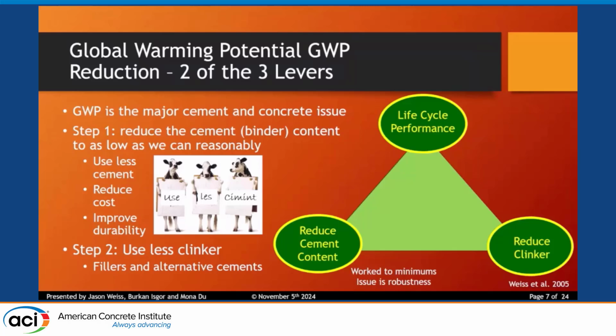I do want to point this out, though, because that was something that helped them with risk before, right? They had some buffer zone in their mixtures, so they've reduced some of that buffer zone to start with. Now we're saying, in addition to reducing that buffer zone, please also reduce the amount of clinker, right? So you see the cows that run around, and they tell you to eat more chicken, right? We want to reduce the amount of clinker that's in the system. This is kind of a new concept that you hear people talking about, but it's really not the cement that's the problem, it's the clinker that's the problem. It's the clinker that has the high GWP in it, right?